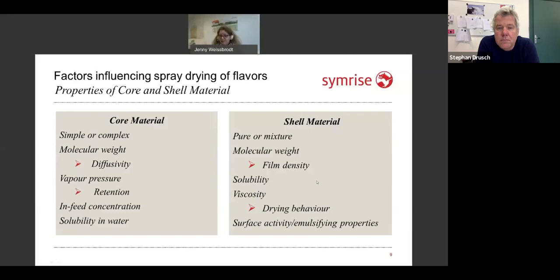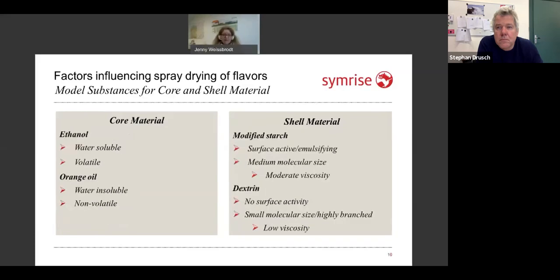You need a high solubility at low viscosity, because then you dry as little water as possible in your process, which makes it more economic. Of course, the surface activity and emulsifying properties are not just necessary for emulsifying your active if it's not water soluble, but they also have an influence on the drying droplet, because a surface active component makes your surface a little bit elastic. And this can be useful in the drying of the droplet, because it will prevent, to a certain extent, the burst of your particles.